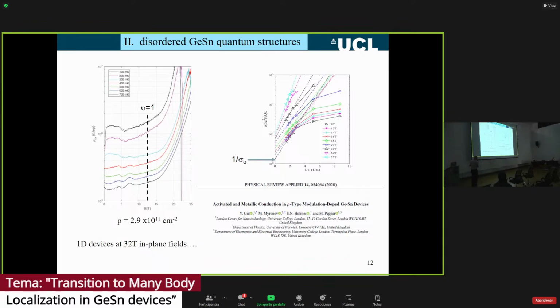But what you can see is, once we get those carriers to that mobility edge, you can see a very, very clear Shubnikov-de Haas effect. And we see a very, very clear quantum Hall effect. I haven't plotted the quantum Hall effect. It's still there, but it's getting swamped by this very, very high resistance. So amazingly enough, we have this localization behavior. Once we get the carriers to the mobility edge, we can see very, very clear magneto-oscillations. What's also interesting is if we plot the resistivity as a function of 1/T at fixed field now, it's a slightly awkward plot. But they extrapolate down to this sigma 0. Sigma 0 is the minimum metallic conductivity. So we see this very, very clear minimum metallic conductivity in the system.